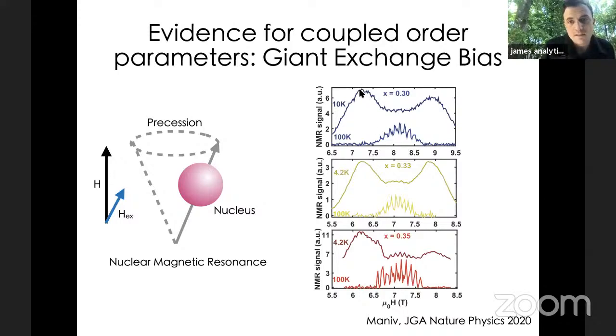The only difference is that the under-intercalated and the over-intercalated samples that you see here have been cooled in field. And there you see that one of the peaks, corresponding to spin up, for example, is bigger than the other peak, which corresponds to spin down. That's because the defects are aligning with one of those environments. That's the way we've understood it.